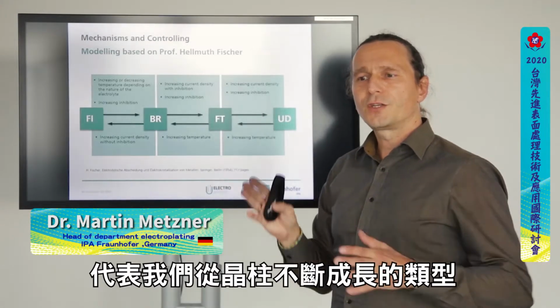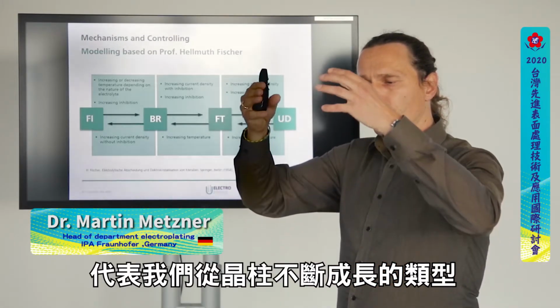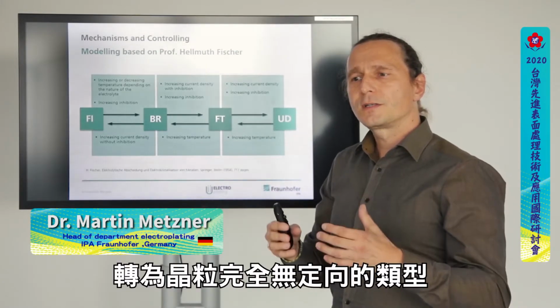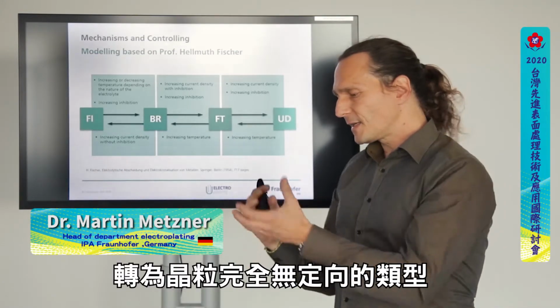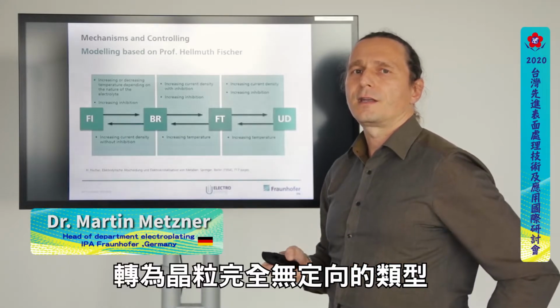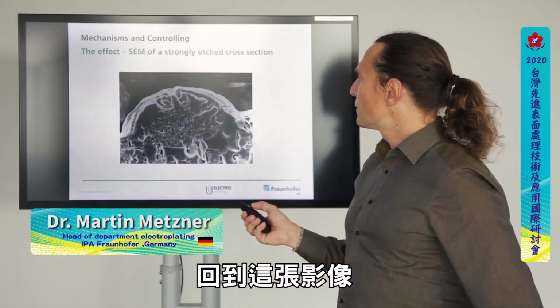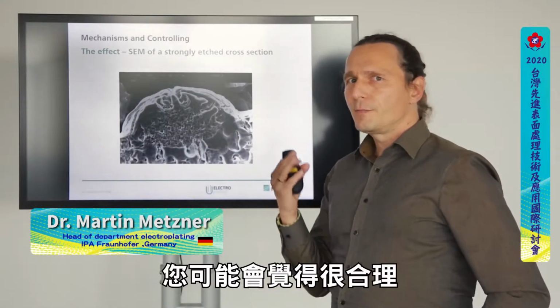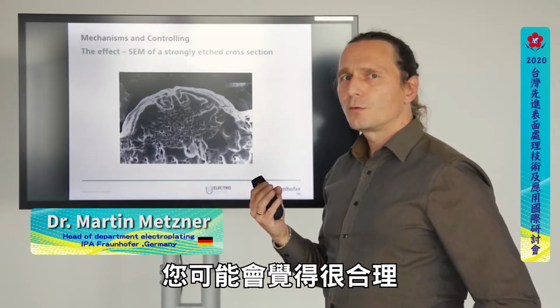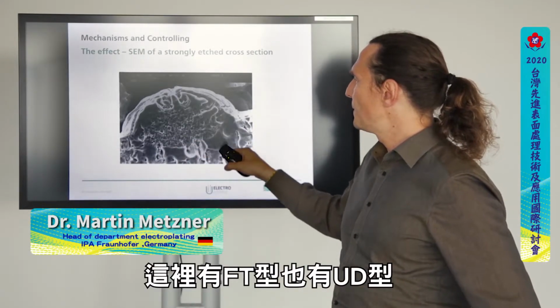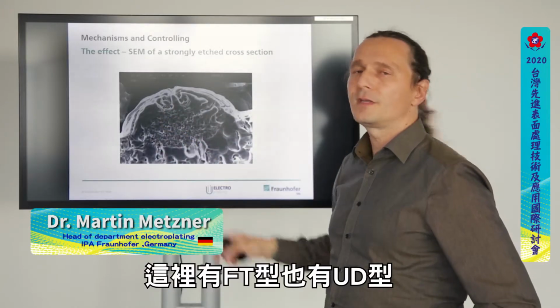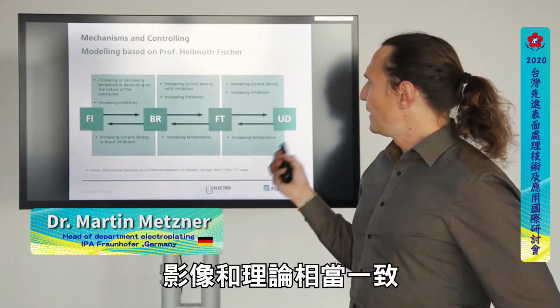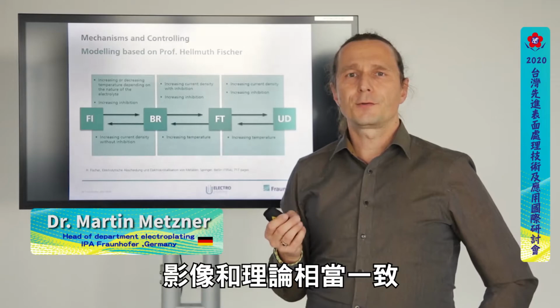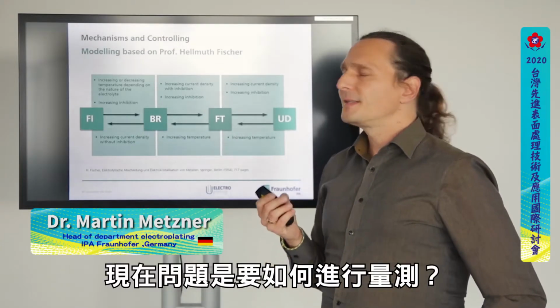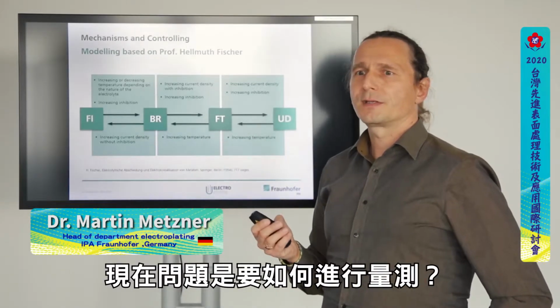This means we change from the type where pillars are growing to a type where all our grains are completely unoriented. And when you go back to this picture, then you maybe can get the impression that this could be right, that we've got the texture type here and the non-oriented type in here. Picture and theory match very well to each other. And now the secret was, how can we measure this?